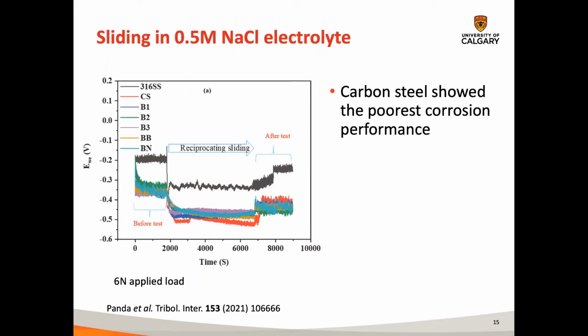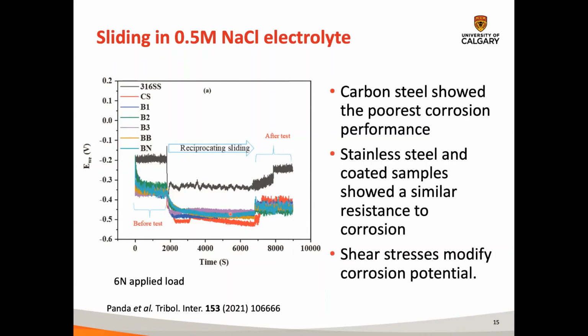And the boronized steels have a more positive value than the carbon steel, but a less positive, or more negative, value than the stainless steel. So they're not as corrosion resistant as the stainless steel, but they're better than the carbon steel. And we see that these boronized steels essentially have very similar corrosion potentials compared to each other, okay?